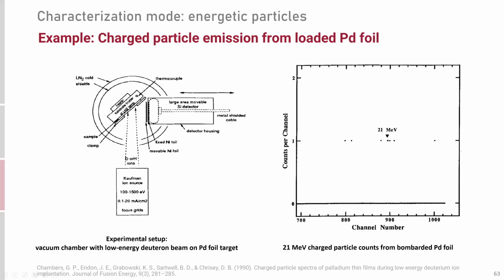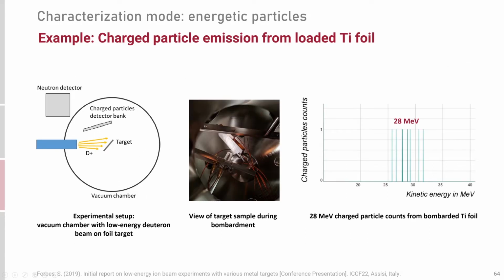There are also reports of high-energy charged particles. In this configuration, a palladium foil is bombarded with low-energy deuterium ions on the order of a few hundred eV. The authors then report detection of a small number of charged particles around 21 MeV. Finally, there's an experiment at MIT where we observed charged particles around 28 MeV from the low-energy deuterium bombardment of titanium foil.